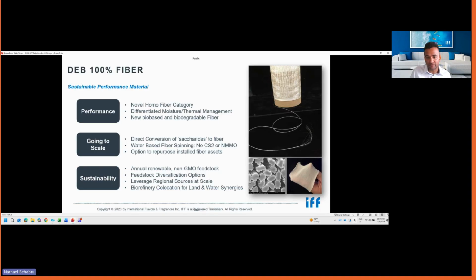From a process perspective, you can really envision a direct conversion of saccharide sugar to a fiber. From a spinning perspective, clearly it uses what is known in the industry, which is wet spinning used for man-made fibers. But unlike cellulose, it does not require carbon disulfide or NMMO in its spinning process. So it's really water-based, where you play with pH to solubilize it and make it insoluble. From a sustainability perspective, this enables feedstock diversification. If you use sucrose from Europe, right, it will be a non-GMO feedstock. And again, it leverages sources that are at scale in various regions.